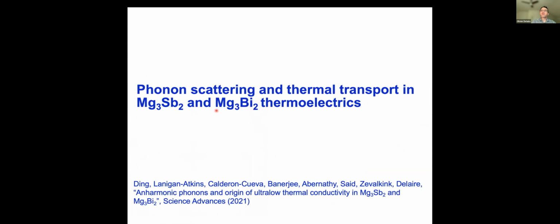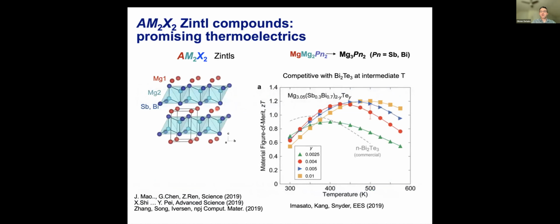So this is a study we did a couple of years ago, looking at this relatively new composition of thermoelectrics that have attracted a lot of interest in this community because these are based on magnesium and generally a pretty cheap composition, and they actually work well around room temperature, so they could displace some of the conventional bismuth telluride type thermoelectric materials. And this composition AM2X2, where the B side here, if you will, is magnesium, and the A side could be magnesium or some other element, as I'll show you, is based on this Zintl structure. This is a calcium aluminum 2 silicon 2 crystal structure, and we'll see that the difference between the magnesium 1 site and the magnesium 2 site in cyan here is important.